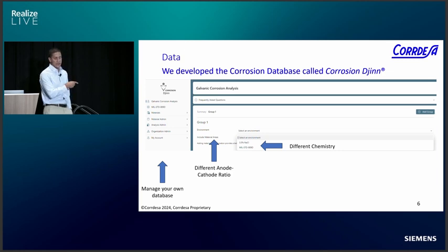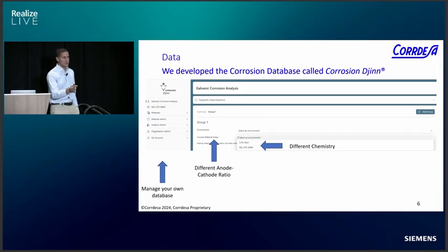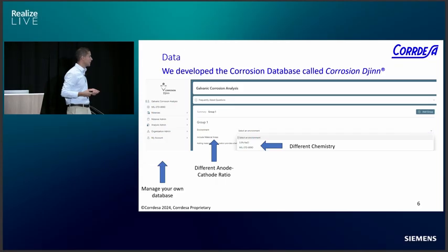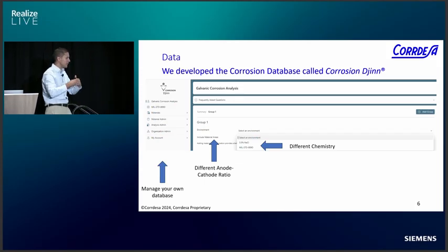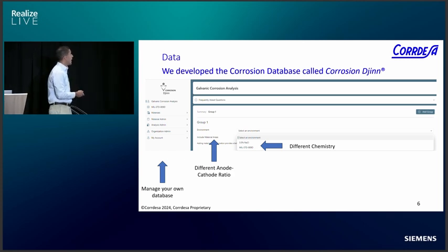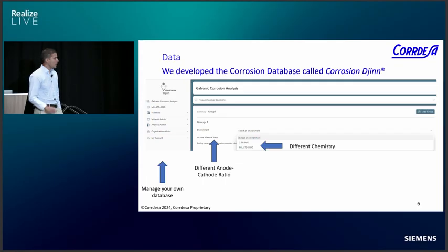Because of that, at Corrdesa we developed, I think it was 7 years ago, our product called Corrosion Djinn. Corrosion Djinn is not only software that provides you information about the corrosion rate, it is also a database management system, which means that Lockheed Martin can say, hey, I need you to add this material that I created for this system in my database. Okay, perfect. Give us the material, we run the test, and we update the database for you for Corrosion Djinn. Another important feature in this version of Corrosion Djinn is that now we can work with different anode cathode ratios, which is extremely important. You will see that shortly.